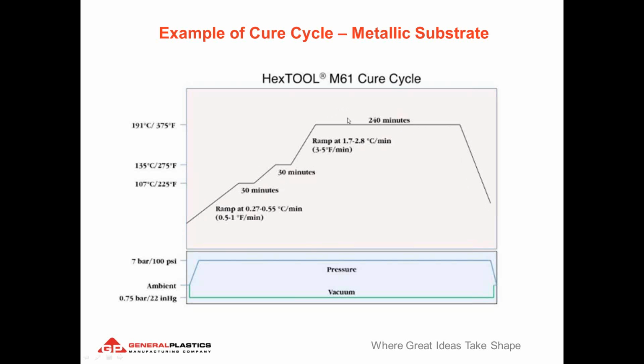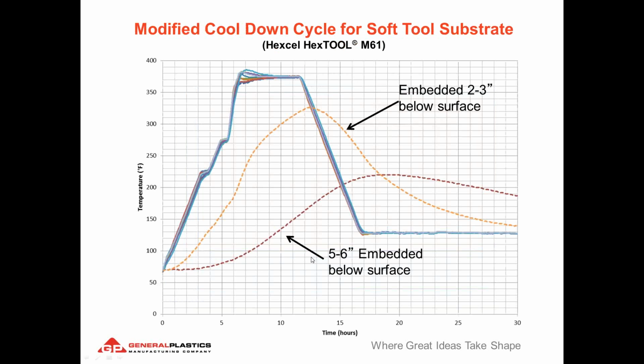So when using a foam substrate, we recommend that you always follow the manufacturer's recommendations on this portion of the curve. In other words, until you get to the end of the high temperature cure. And depending on what you desire for your foam afterwards is where we get into how to modify the cool down cycle. So in an oven, we have looked at a cure profile using the same profile, and all these lines on here are just different parts of the oven to show that it's all uniform temperature in that oven. So we have the same steps, the same maximum cure profile up here.